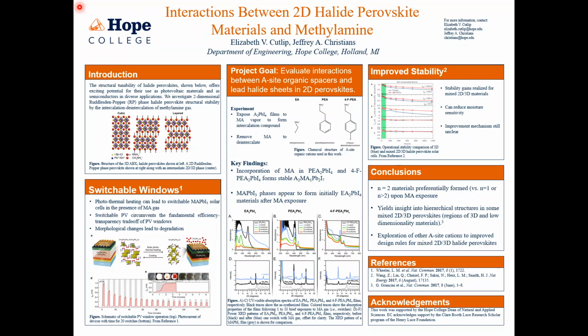Perovskites have the capability of switching from their colored, light absorbing active phase to various different structural phases where they are visibly transparent. You can see this in the image at the bottom left of the poster. While there are other possible color changing mechanisms, the structural change shown here and throughout our work occurs because of MA gas intercalation. This color-changing property is what sparked the idea of color-switchable solar windows, which was pioneered by Lance Wheeler and others at NREL.